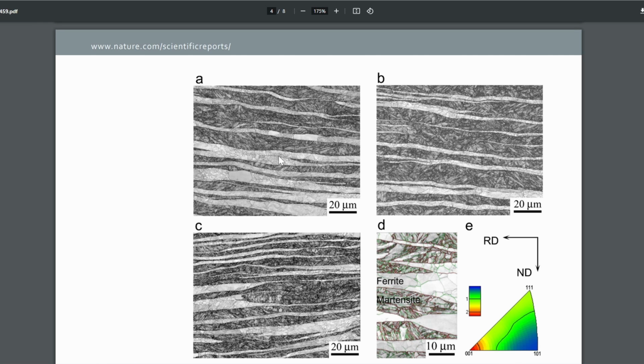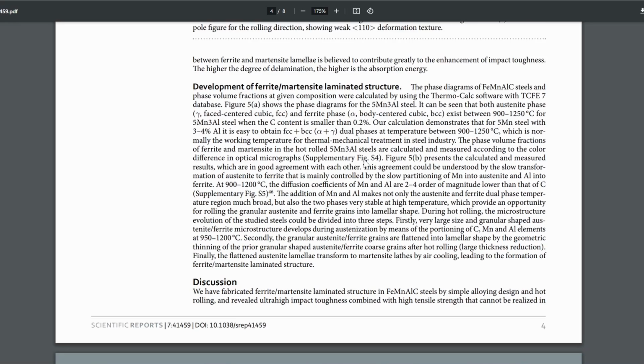Okay, so I pulled up this article, and this is the laminated ferrite/martensite microstructure that he's talking about. In knives, we are familiar with laminated steels and Damascus, but this is not laminating two different steels together. The laminated microstructure it's talking about is within a single steel. Through specific alloying and processing, they hot rolled the steel where it had both phases, ferrite and austenite. And when they quenched the austenite, it formed hard martensite. So this is a mixture of soft ferrite and hard martensite. And it looks laminated because it was formed during hot rolling, so everything is elongated. So that's the first thing to mention.